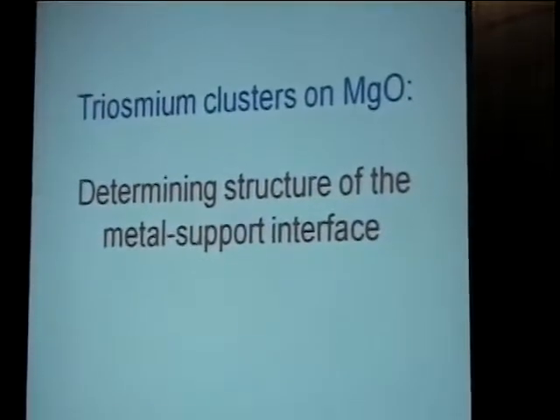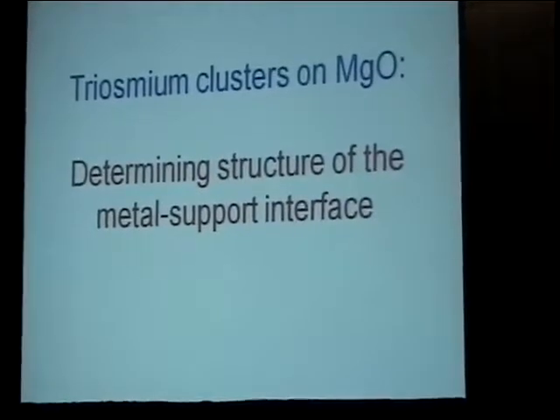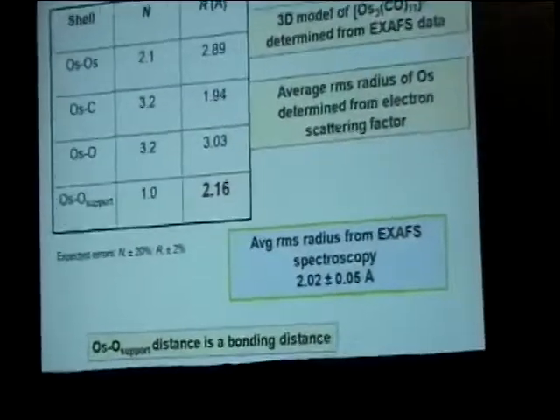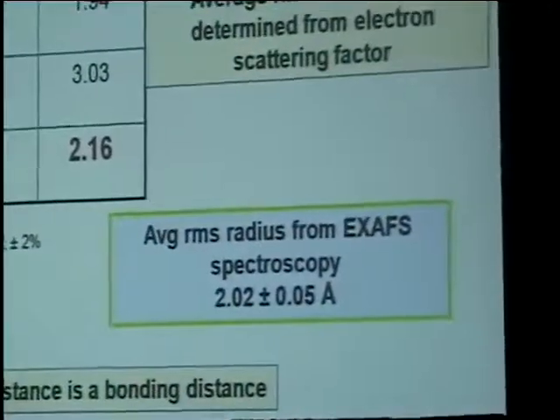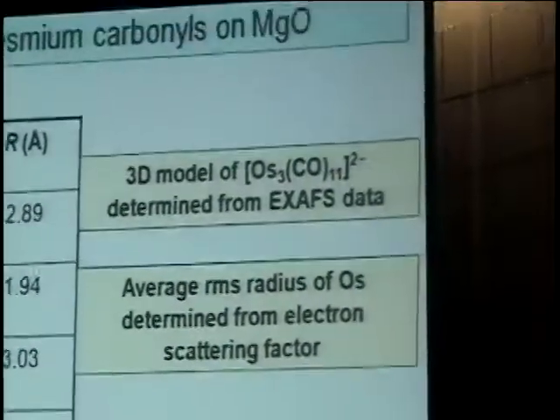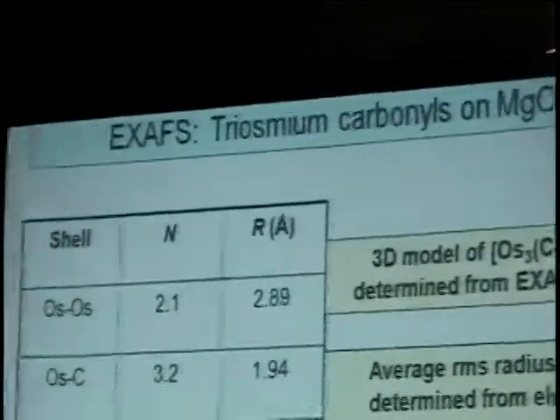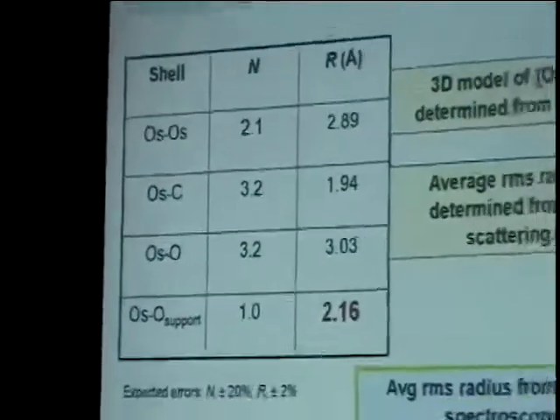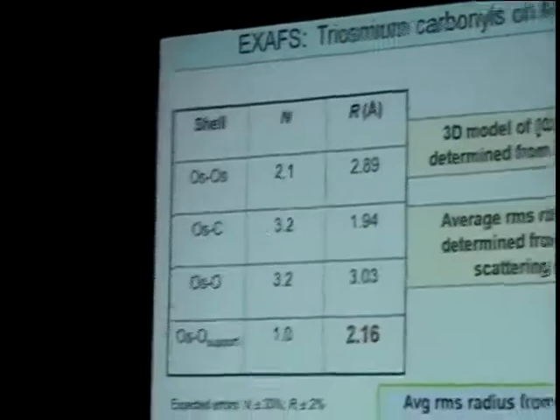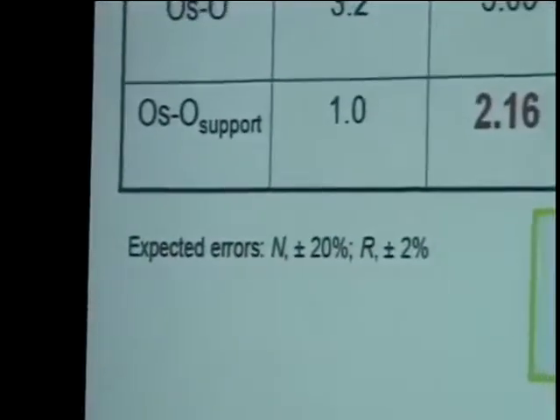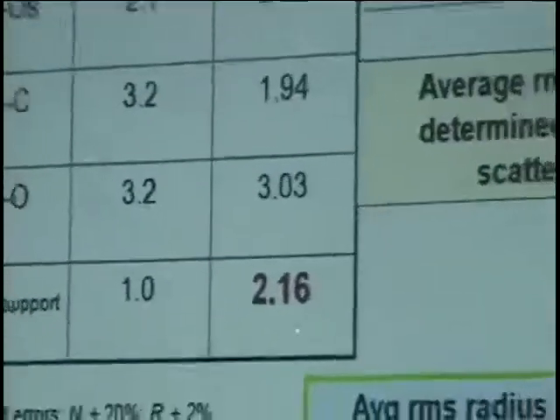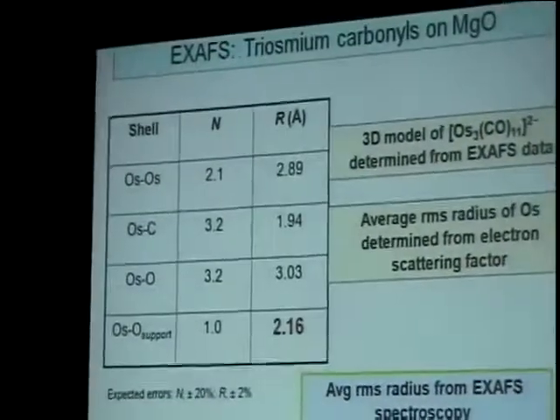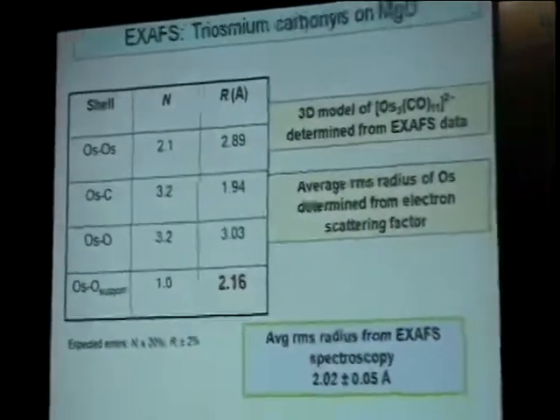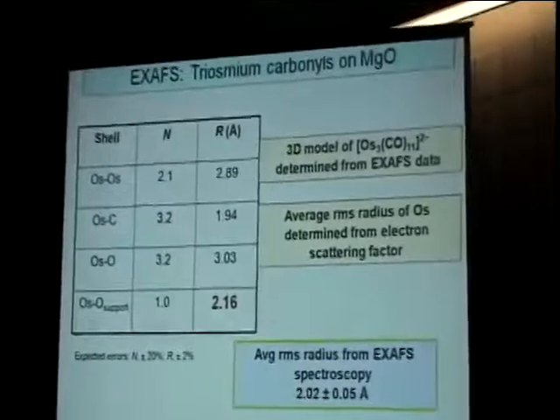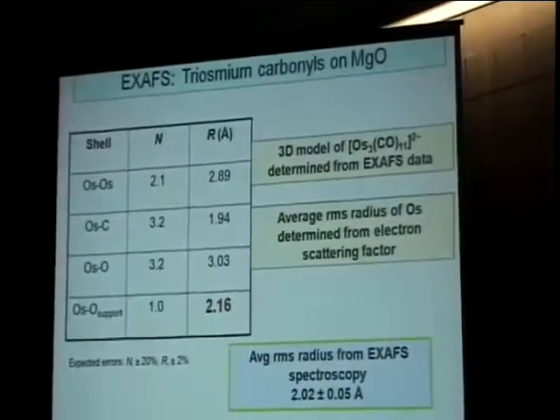Now let's go back to the triosmium because we can learn about the interface structure here as well. So I'll show you a few XAFS. The osmium-osmium coordination number is about 2, as you expect for a triangle, so the triosmium is intact. And even with this as a metal carbonyl, all these are metal carbonyls, the osmium-oxygen distance here is about what I showed before, with an error I would say close to the same. This is a bonding distance, even though we still have carbonyls.